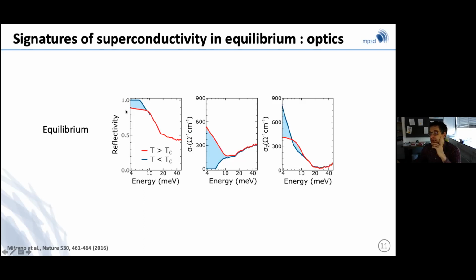So if you take a superconductor like C60 at temperatures higher than the superconducting transition temperature, that is in a metallic state, what one finds are optical properties that are reminiscent of a metal. There is a reflectivity edge at a certain frequency that depends on the density of free carriers, a real part of the conductivity that is a finite DC number and then rolls off at a frequency that is approximately the scattering rate. And then there is an imaginary part of the conductivity, the out of phase response of the current when I apply an AC electric field, which is peaked at the scattering rate. So this is basically the Drude response of a metal, which changes drastically when it becomes a superconductor.